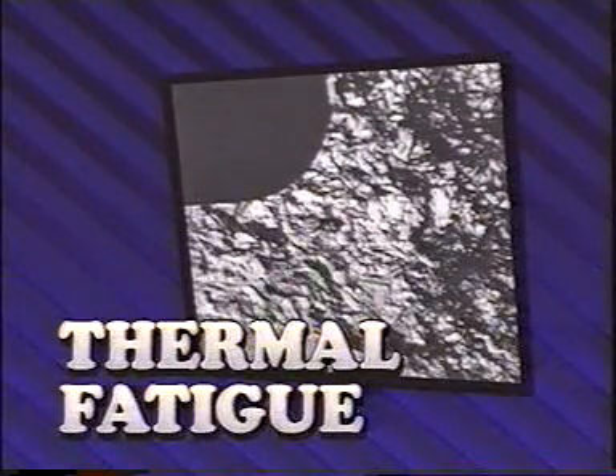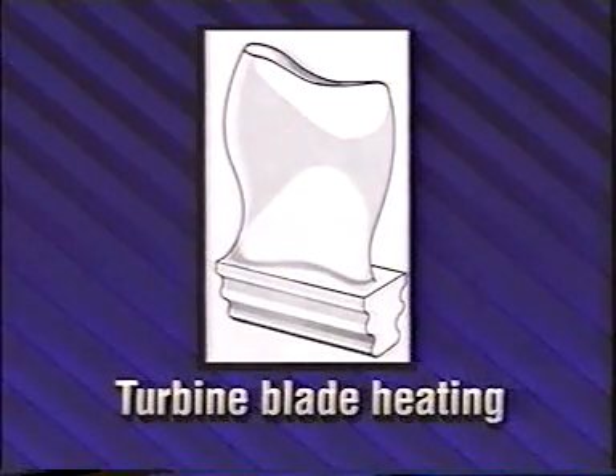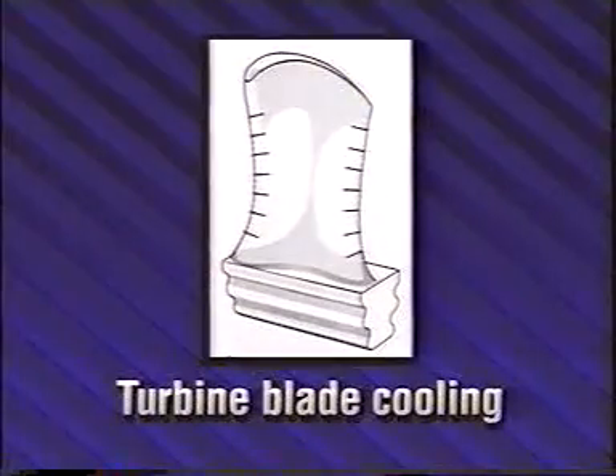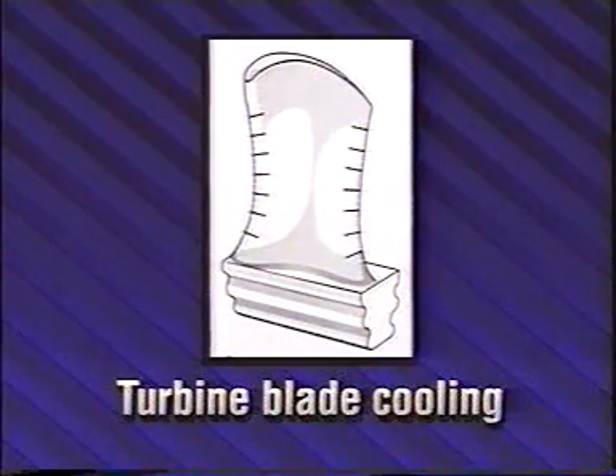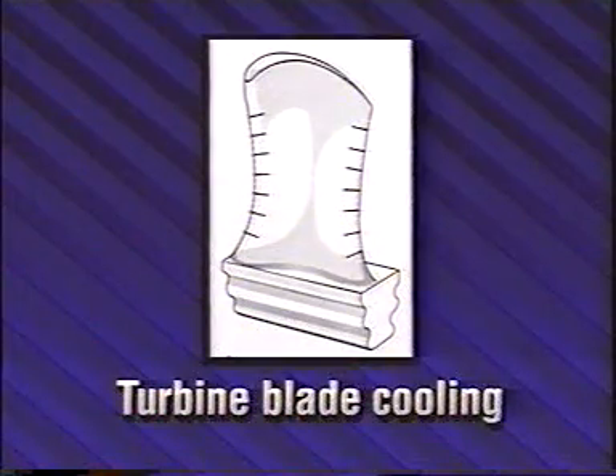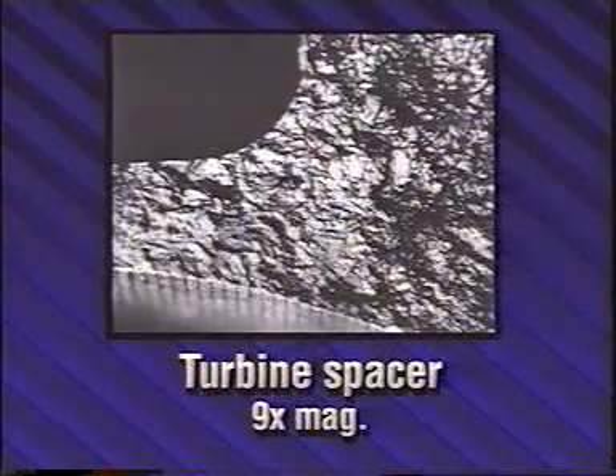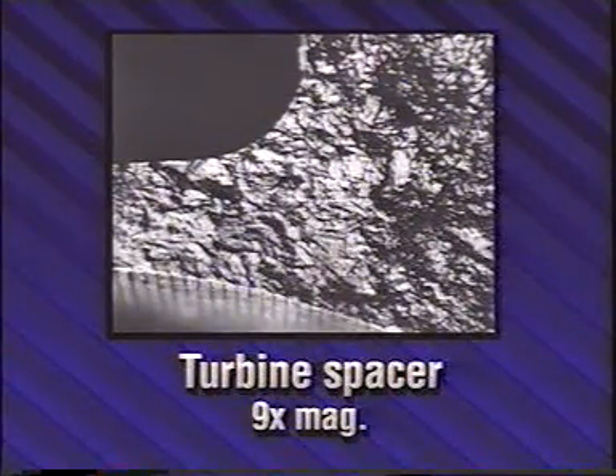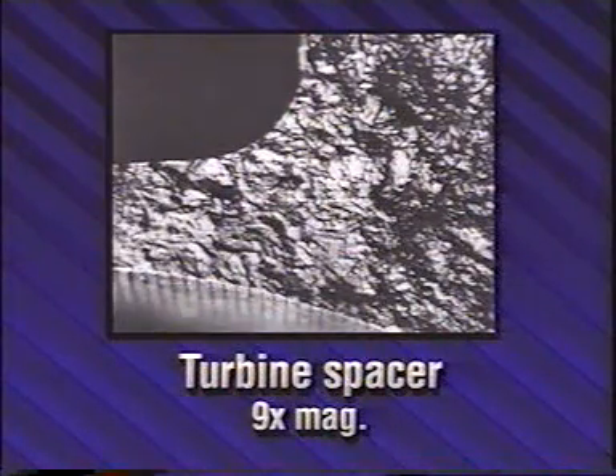Thermal fatigue. Mechanical conditions are not the only sources of cyclic loading that can cause fatigue failure. The cyclic effects of elevated temperatures can cause thermal fatigue. Temporary localized thermal gradients within a component can induce plastic strains. If these thermal gradients are applied repeatedly, the resulting cyclic strain can induce failure. The cracks caused by thermal fatigue usually initiate at the surface. They originate perpendicular to the surface and may occur singly or in multiples. The cracks then gradually propagate inward,